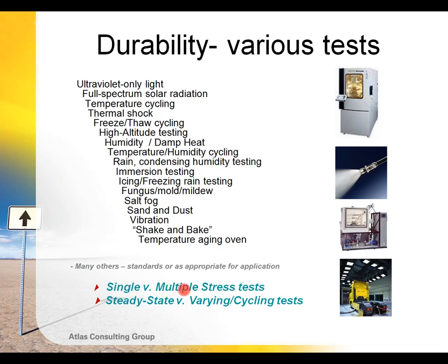When we start getting into multiple stresses and cyclic stresses, then we start also looking at interaction effects. So it's important to understand that if I simply test to single stresses, especially at steady state, which almost never happens in actual field use conditions, I very often may be able to detect a sensitivity or a failure related to a single stress, such as water immersion or elevated temperature, such as the ice cube melting. But I can't detect interaction effects, such as a coating failure that may occur only with UV exposure in combination with high levels of moisture. Okay, so at each different type of test, at each different level, I get different amounts of information.